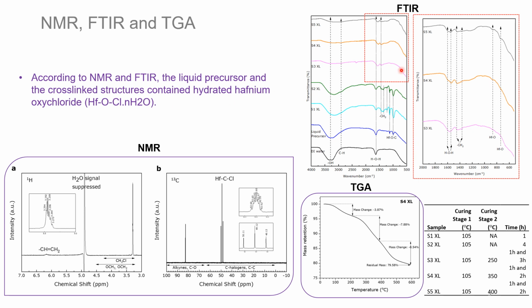Here in the FTIR plot, as the cross-linking temperatures increased from 105 to 400 degrees C, the intensity of the vibration bands for the water molecules decreased significantly due to the release of water. For these three samples, S3 to S5, the magnified image of this region is shown over here. Here we see a shift in the peaks, which are presented here around 1600 per centimeter. This supposedly happened due to the coordination of cations in the cross-linked structures of hydrated hafnium oxychloride. Absorption peaks corresponding to monoclinic hafnia were also vaguely visible at lower wave numbers for this sample.